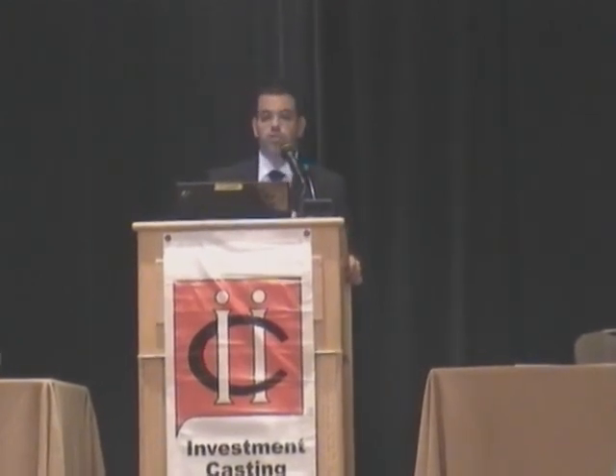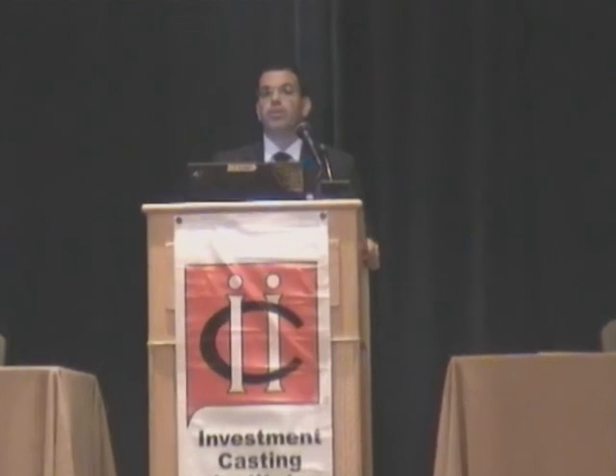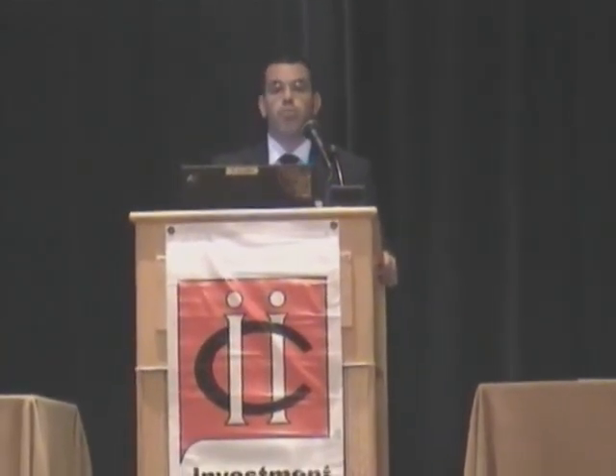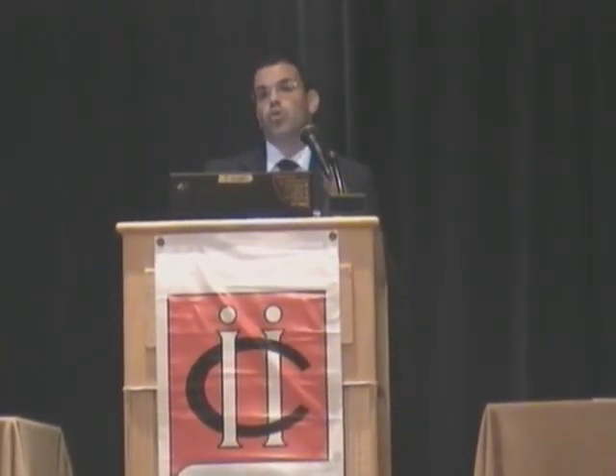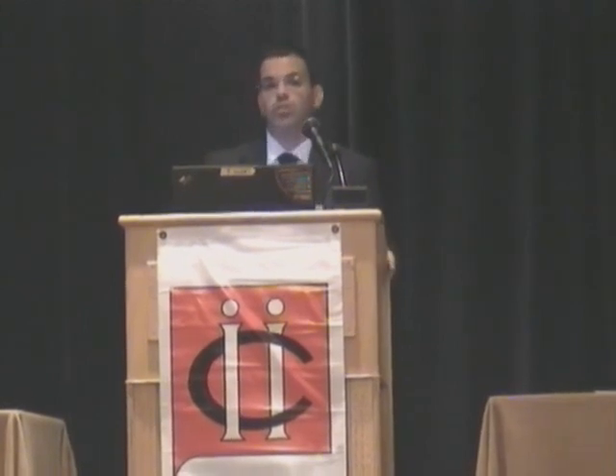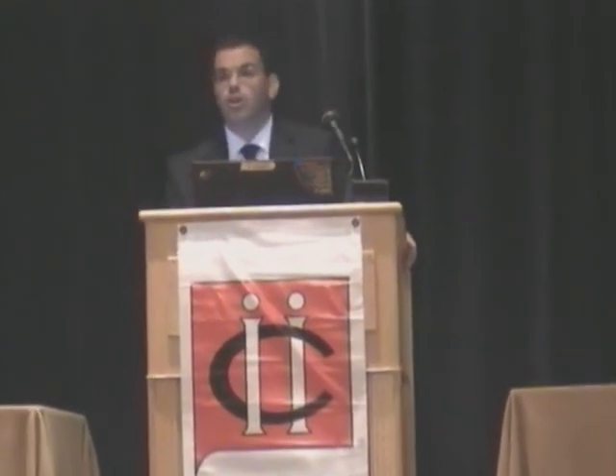Modification to some of the foundry equipment and improvement in the process results in an increase in part size by more than 40%, just by running modification to our equipment, just by going towards a certain particular casting method, which is the vacuum process. As most of you probably know, it allowed us to increase the size of parts we were pouring by more than 40%.